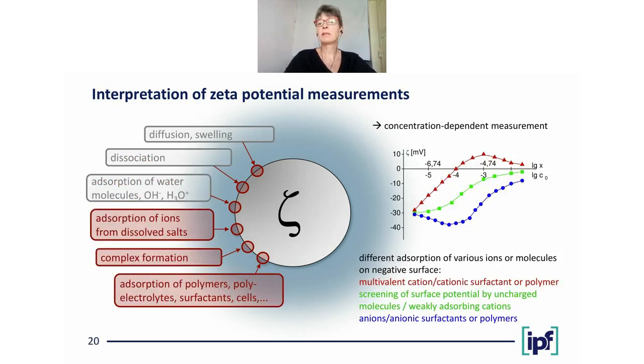Another possibility are concentration-dependent Zeta potential measurements. Here we see some typical curves for strongly adsorbing cationic species, for instance, multivalent cations or cationic surfactants or polymers. This is the red curve. These species lead to a charge reversal of a negatively charged surface. If we have strongly adsorbing anions, we see an enhancement of the negative charge.